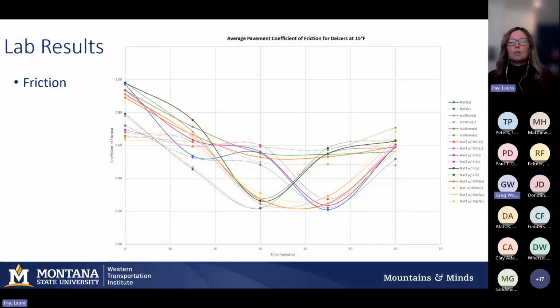So I think the big takeaways here are that the pavement type had a significant influence on the results, and that for the different additives that were added, they influence the friction at different times. And so that may have to do specifically with the additive type and the product mixture. And more work would be needed to really tease out what was going on there.